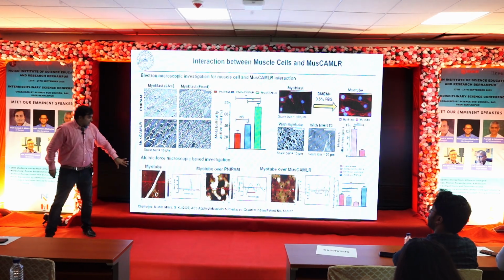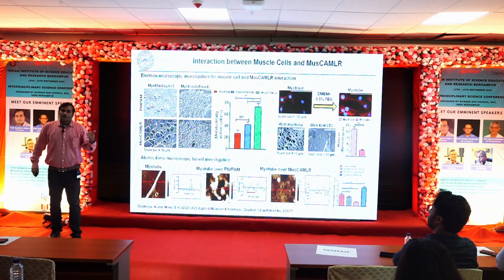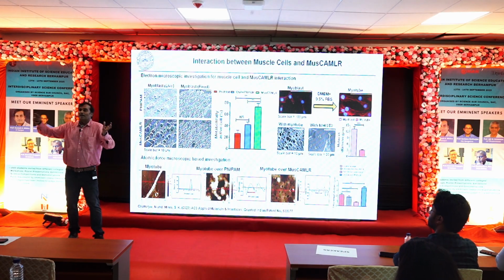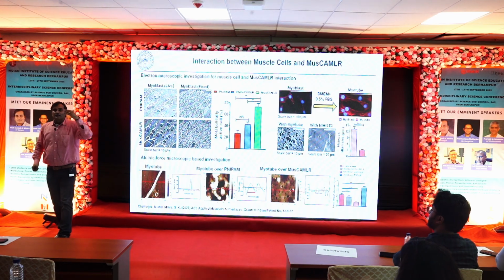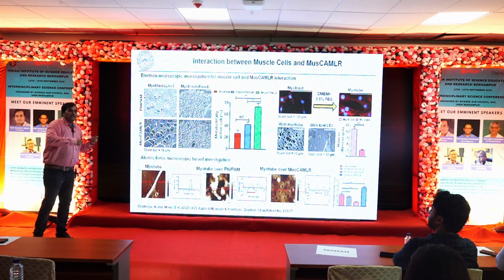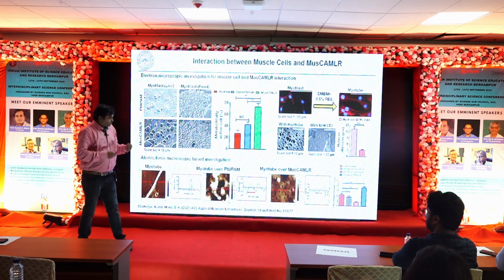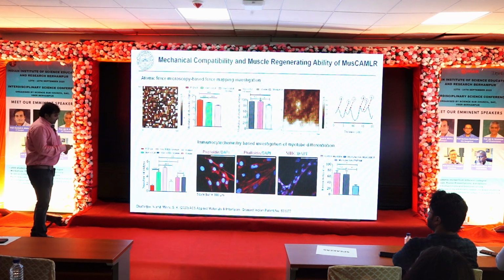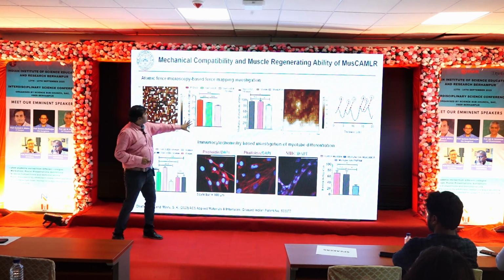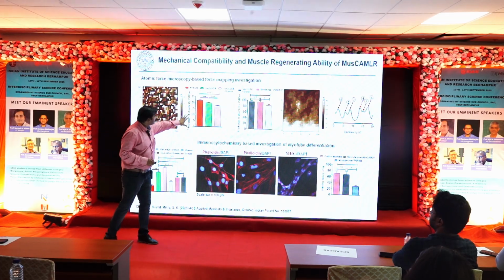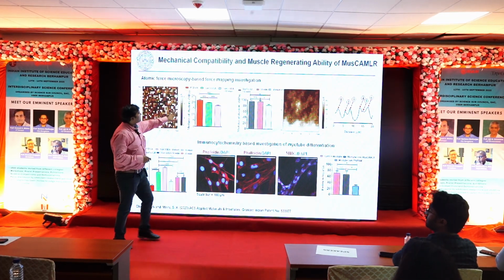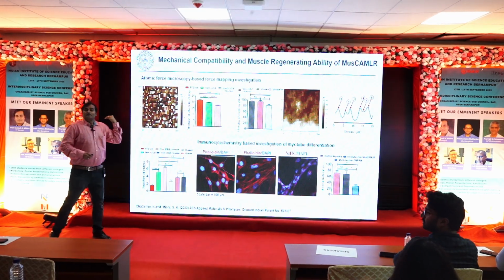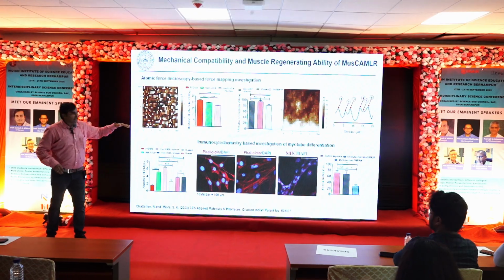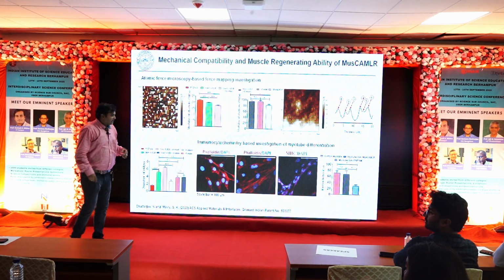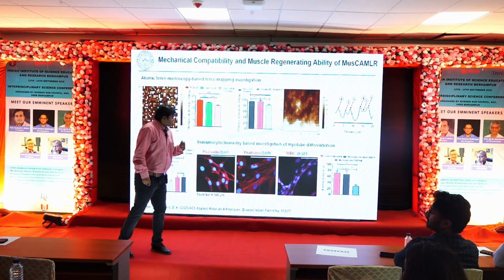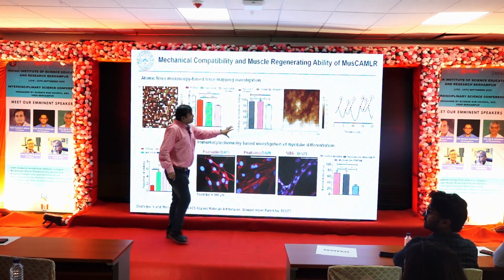Then we wanted to see what the mechanical forces are. So we took the AFM route, we did AFM analysis of the primary cells, the myotubes and our material, and we found they were very much matching what we initially expected. Here you can see more analysis. I'm not sure how clear it is because it's not clear to me, I'm very close to the screen. But anyway, what we found was that the mechanical strength was very much matching with the original tissue which we collected from the in vitro system. Then we tried to match the number of ridges.